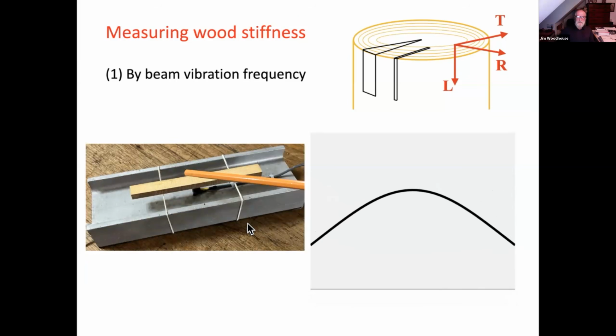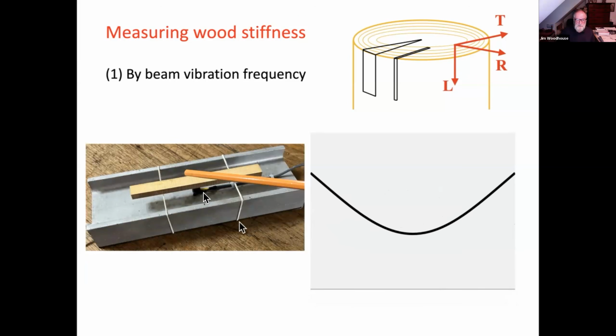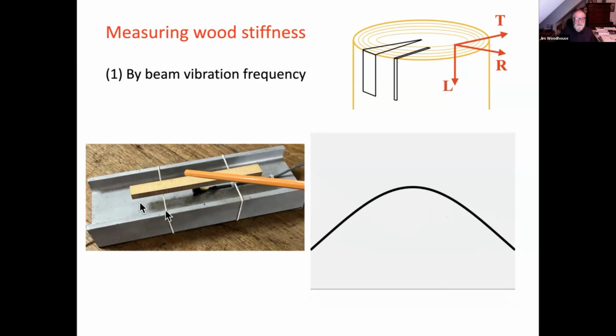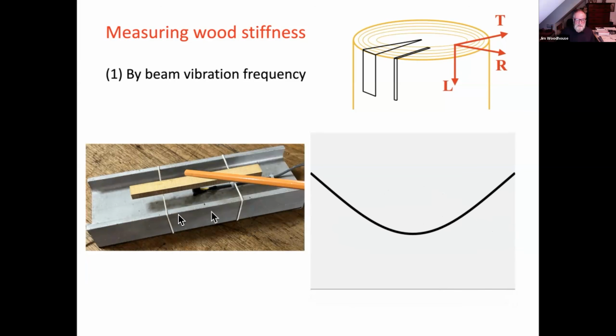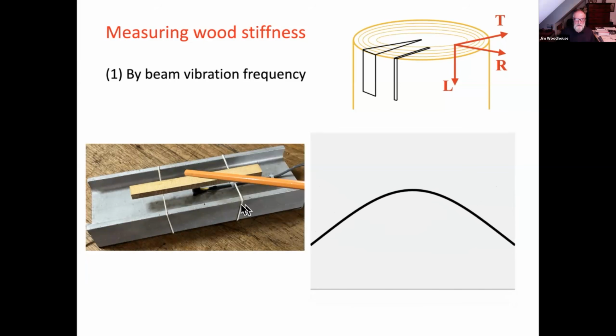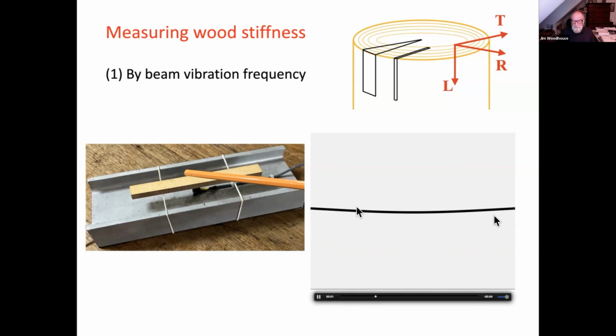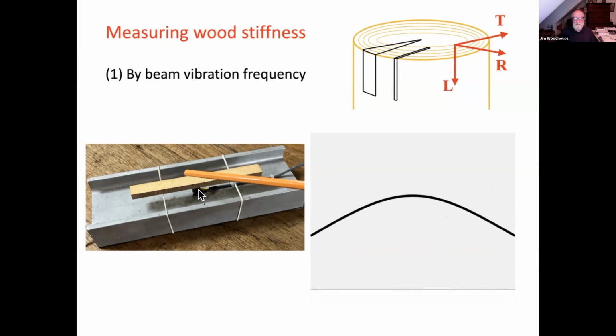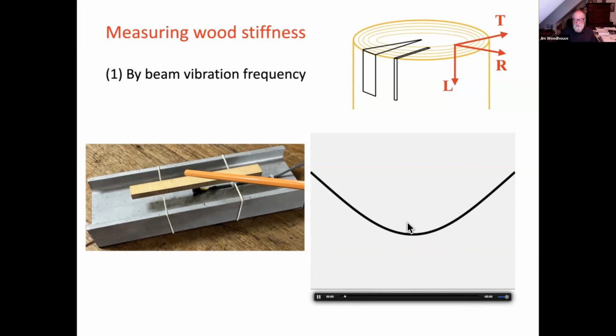Here's how you might do that. This is my favorite way to do that measurement. Here is one of those spruce samples. So this is just a piece of U-channel, 2 rubber bands so that you can move them around, and you slide them up and down so they're roughly under the 1/4 and 3/4 points, which are the nodal points of this vibration mode. You tap it with a pencil, put a little microphone underneath, grab that into your FFT analyzer, and with a bit of luck, you'll see a clear peak going with this lowest vibration mode.